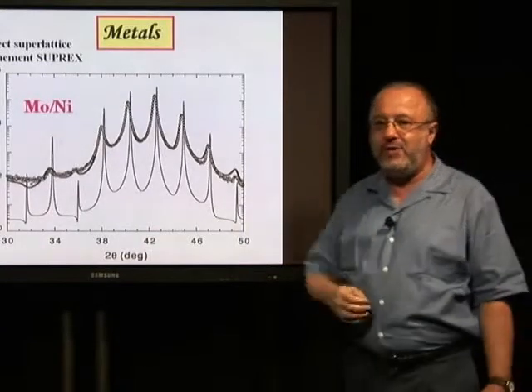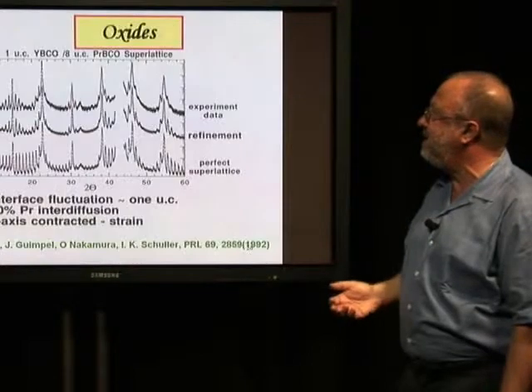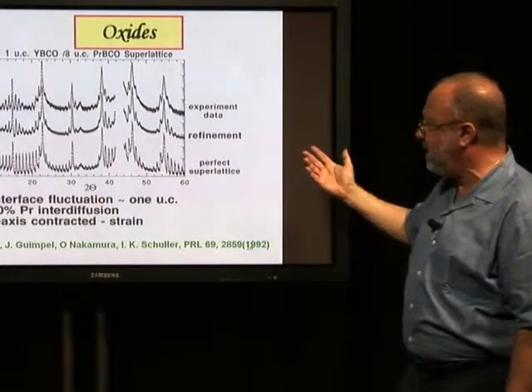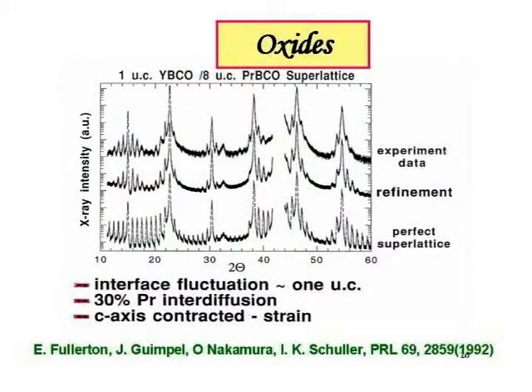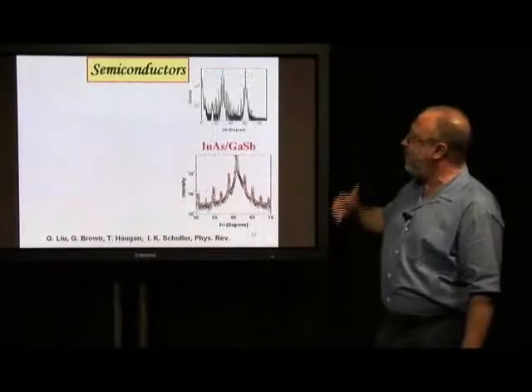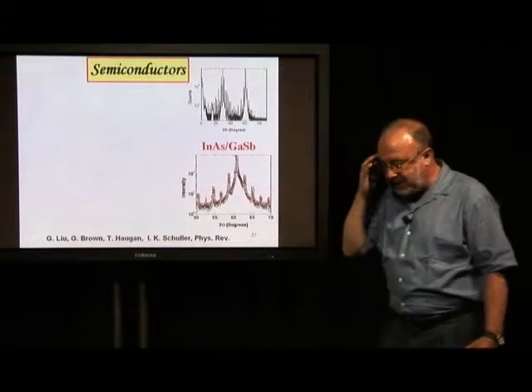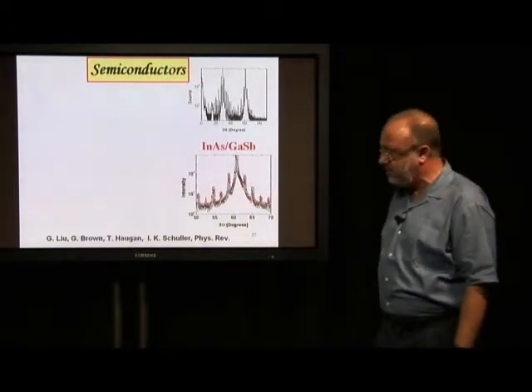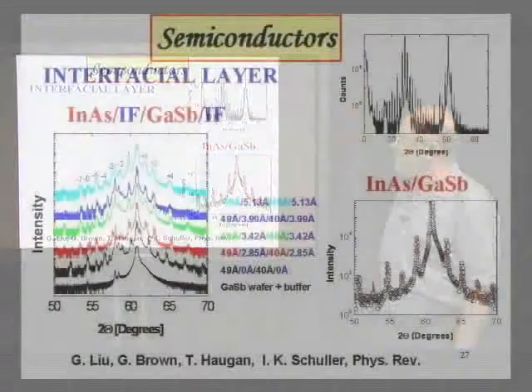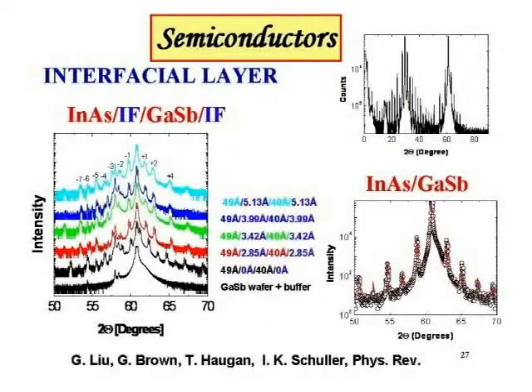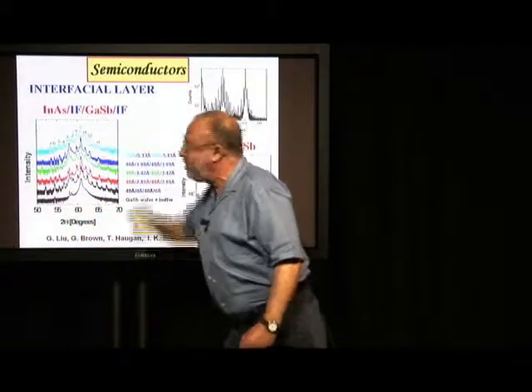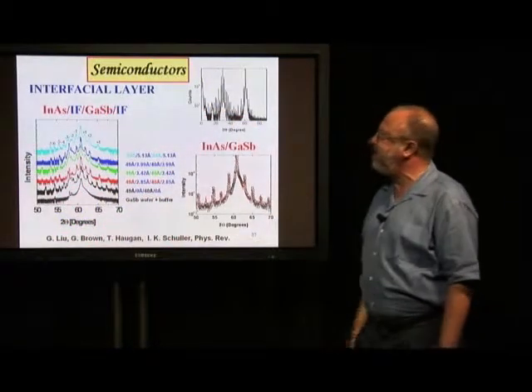Now, years after, this has expanded to many other areas. For instance, this is in oxide superconductors, high TC superconductors, YBCO and praseodymium BCO. Again, the experimental data, the perfect superlattice doesn't fit. The refinement fits it quite well. It went to semiconductors. These are some semiconductors, indium arsenide, gallium antimonide, which are used for infrared detectors. These are very recent work, just recently published, where we can tell something about what happens at the interface between the indium arsenide and the gallium antimonide, what happens to that interfacial layer, and how to optimize these structures.